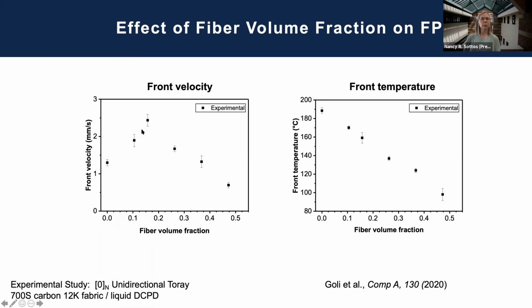And that's because the fibers are actually more conductive and let the front propagate more smoothly across the panel as we show. Then as you start to add more fibers and we get to a higher volume fraction material, that front starts to slow down again and can actually stall or be in danger of stalling because, again, you have less monomer there. And so you have to be cognizant of that in your processing. In addition, the maximum front temperature is coming down as I add more fibers because the front is less hot due to the heat dissipation. And that's also important.